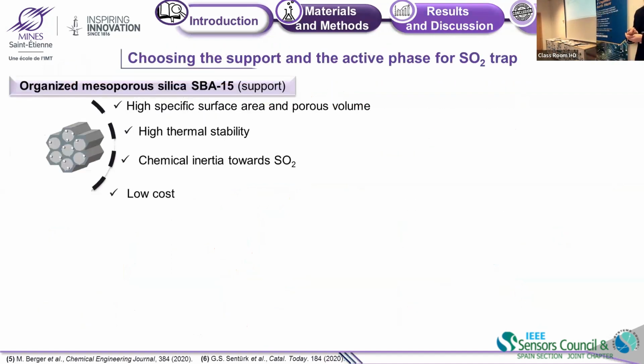To do that, we will choose a support and active phases. The trap will be composed of an organized mesoporous silica called SBA15. This support is known to have a high specific surface area, a high porous volume, and a high thermal stability, because this trap will also work at temperature. It is chemically inert towards SO2 and it is a relatively low cost support.